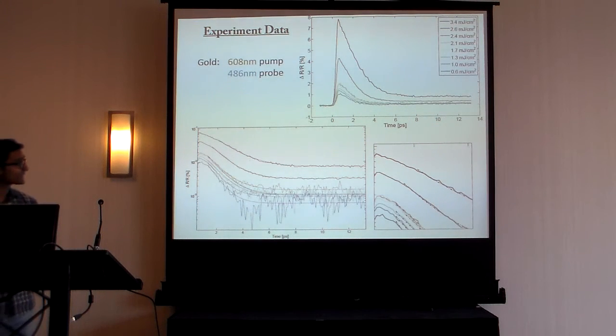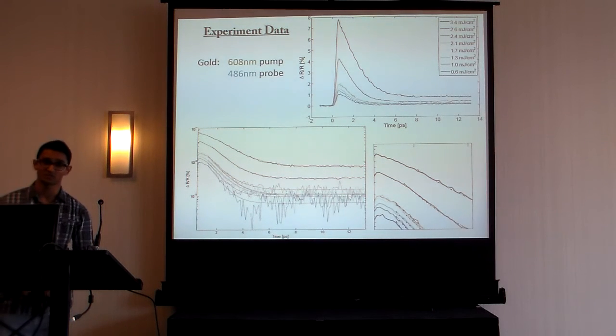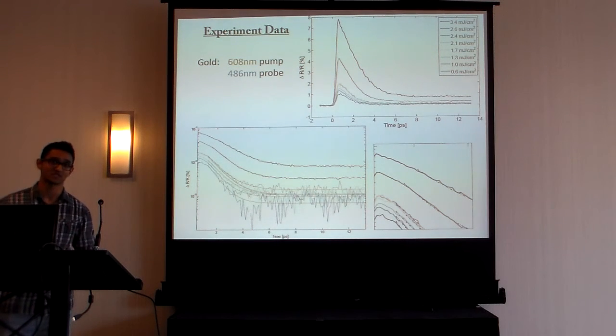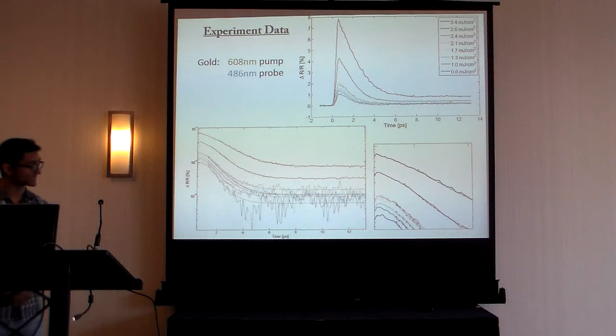On the bottom left, we show the same plot on a semi-logarithmic scale, and the dotted lines are applied exponential fits plus a constant. The graphs are not perfectly linear because there is a background signal which skews that. On the right, we have a blow up of the peak change in electron temperature or reflectivity signal, and you can see that we started our fits roughly 1 picosecond after the peak electron temperature because we want the hot electron gas to thermalize within itself, so we can understand.